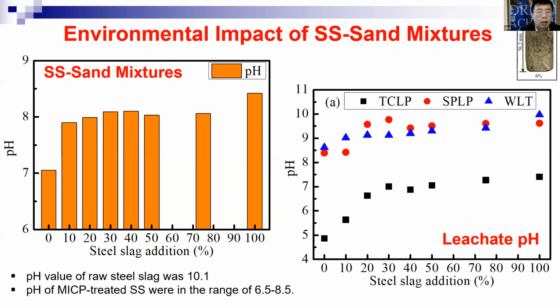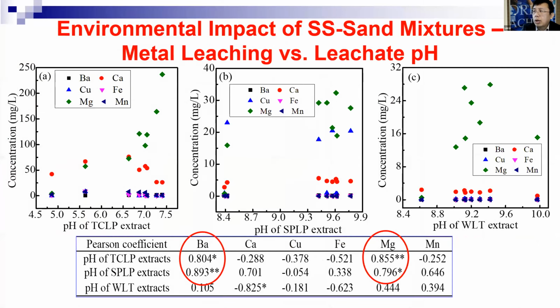But for SPLP and water leaching testing, the final pH reached about 9.6. We can see, compared to their original extraction fluid pH, that the pH is increasing, which indicates it has strong acid neutralization and the ability to resist acid corrosion for the MICP-treated steel slag products. That's one thing, because later when we look at the metals, we want to see what kind of relationship there is with the leaching.